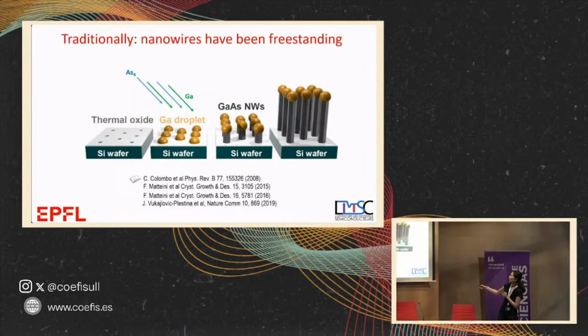And so what you have is the liquid gallium, the arsenic diffuses through it and creates gallium arsenide. It's like if you put too much sugar in your coffee, it stops at some point being sweeter because there's too much, so it precipitates because you reach supersaturation of the coffee. So it's the same here. We keep putting arsenic in the gallium droplet. At some point, it solidifies as gallium arsenide, and that's how you create a gallium arsenide nanowire.